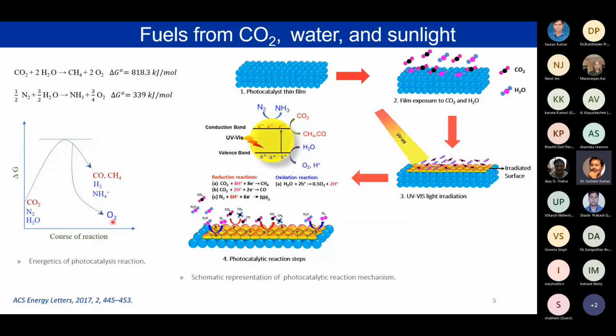The reason is, when we were doing the experiments, we keenly observed that when we were preparing or synthesizing the catalyst and performing the experiments in the liquid phase, there were some products like acetic acid or some other hydrocarbons, which could result not from the reactions but from other ways or the synthesis process, and that could be erroneously misinterpreted as the product. So to rectify those things and to understand these kinds of reactions, we prefer to work in gaseous phase reactions.